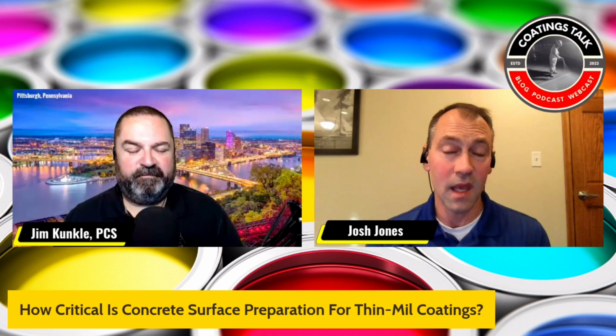some of their material that's not a part of the slab. If I have a failure down the road, they're going to pull up that coating and look at the back of it. Anything stuck to the back of the coating, especially if it was also on the back of the tape, it didn't adhere because I didn't prepare it properly. It wasn't clean. So the coating didn't fail, it just didn't stick. So that's a very simple test as well.